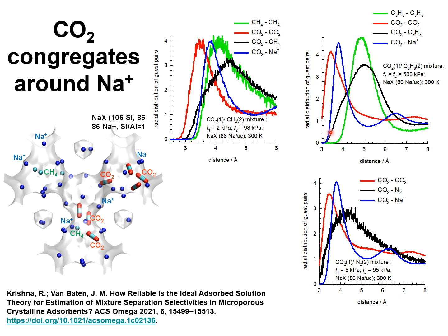The distance between CO2 and propane molecules indicated by the black line is significantly larger than the distance between two CO2 molecules. So the propane molecules are located further away from the CO2 molecule, leading to segregation.